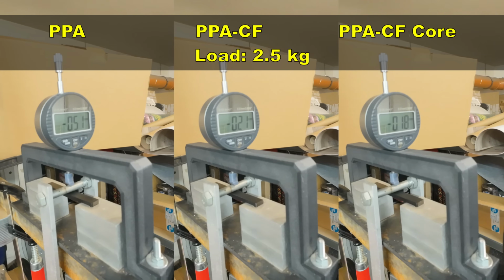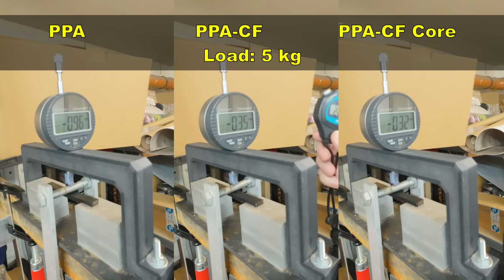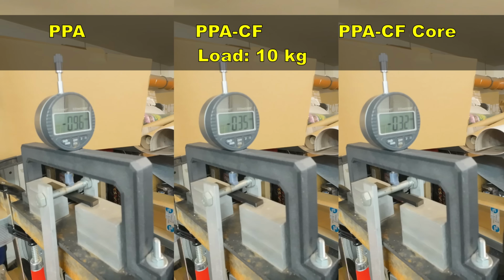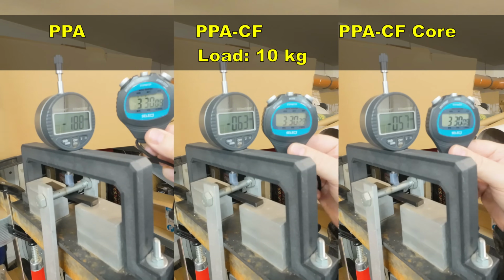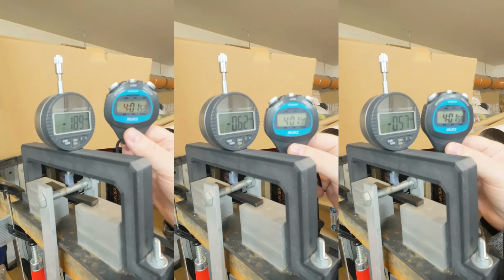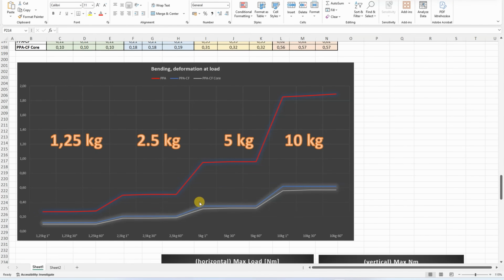Currently you can see the deformation under 2.5 kg, under 5 kg, and this is under 10 kg, and basically almost no additional deformation on carbon fiber versions. The deformation on two carbon fiber versions is very similar, slightly less on the core version. Now the PPA has more deformation, but the additional deformation during the time is very minimal, so it really handles this bigger load well too.